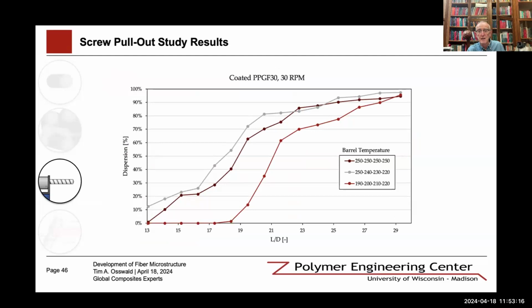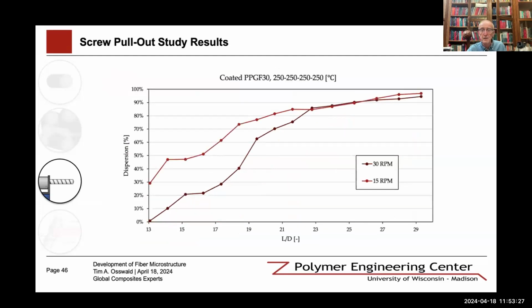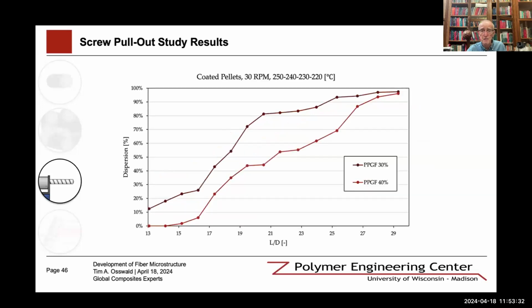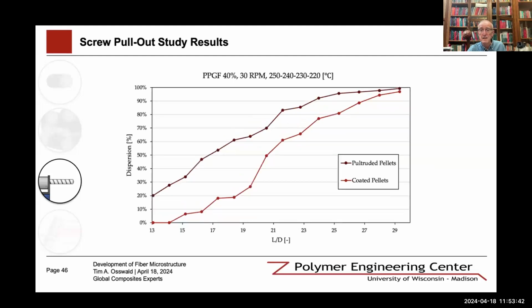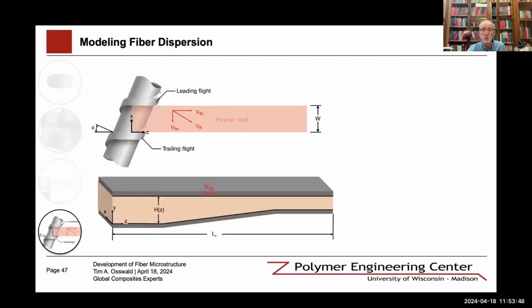So dispersion using different parameters along the extruder, along the different L over Ds. You can see we reach almost 100% dispersion at the end. The different RPMs, 30 RPM, 15 RPM. You can see how dispersion is affected by that. Glass fiber 30% and 40% with the coated pellets. So the fiber density, comparing pultruded pellets versus coated pellets in this dispersion. And we then joined that to a model, and this is just a very brief analysis.